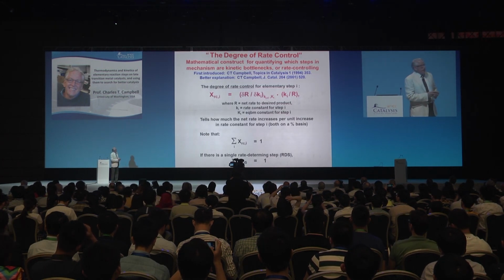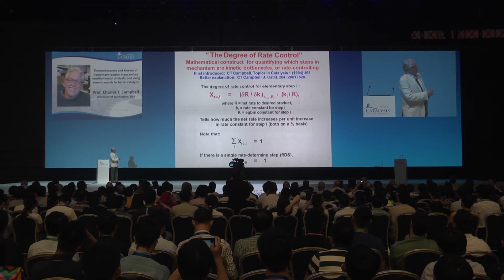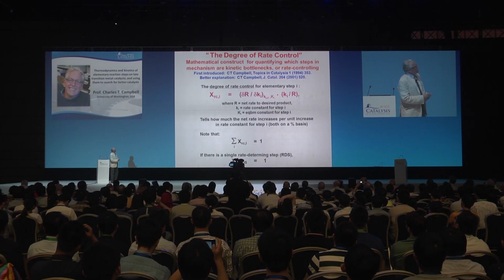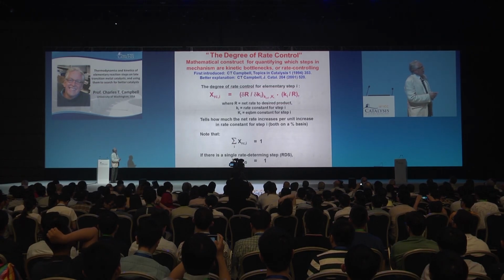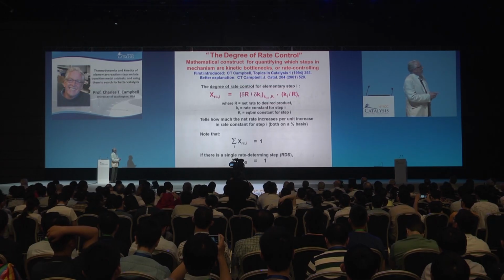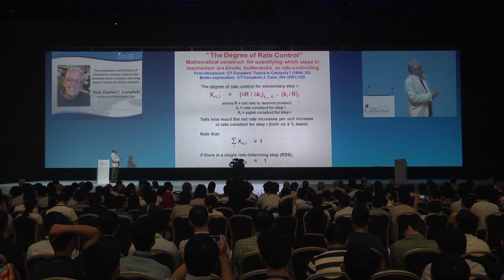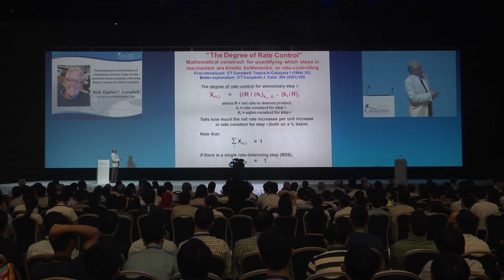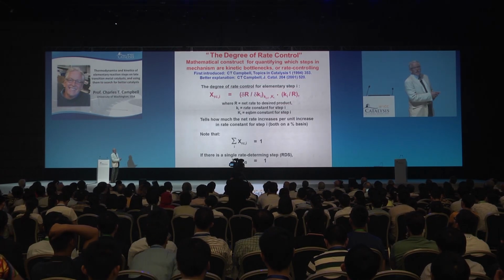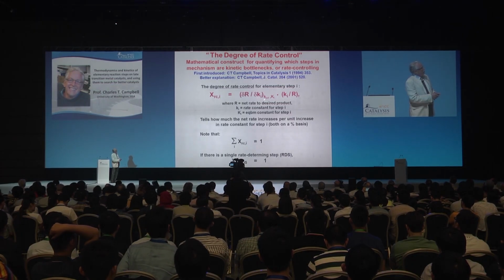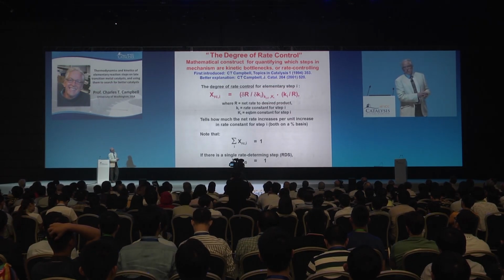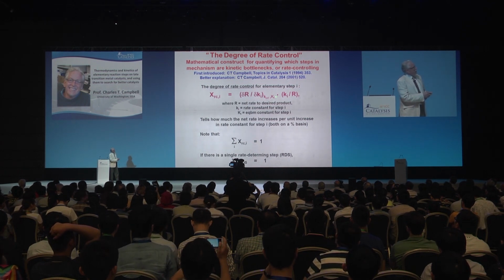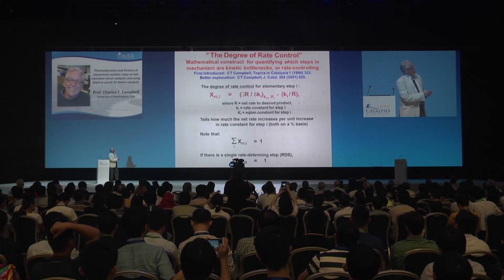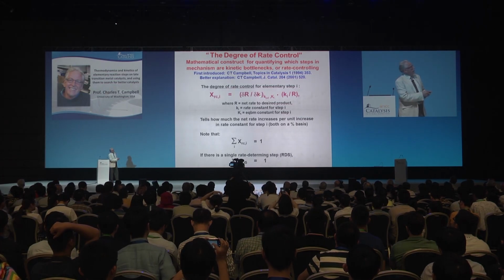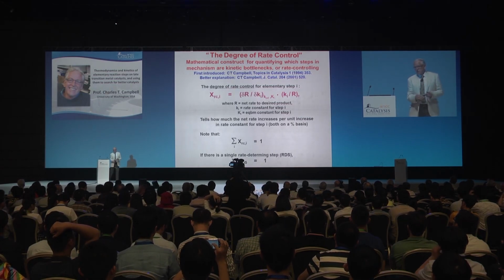So we've discovered that in analyzing these kinds of microkinetic models, there's a concept that we invented called the degree of rate control for elementary step i that is a powerful tool. It's the change in the reaction rate per change in the rate constant for elementary step i, holding the rate constants for all the other elementary steps in the mechanism, and the equilibrium constant for that step, constant. And it's normalized in this way so that it's really the fractional change in net reaction rate to the product of interest per fractional change in the rate constant for that elementary step.